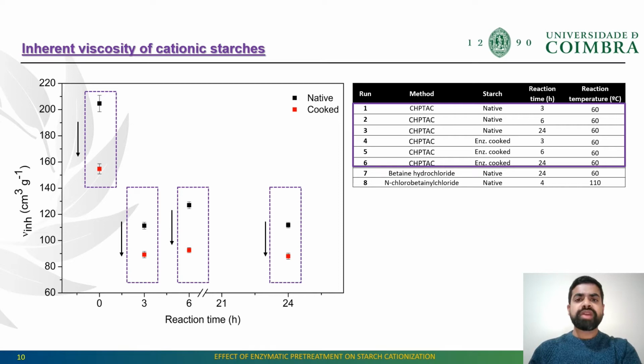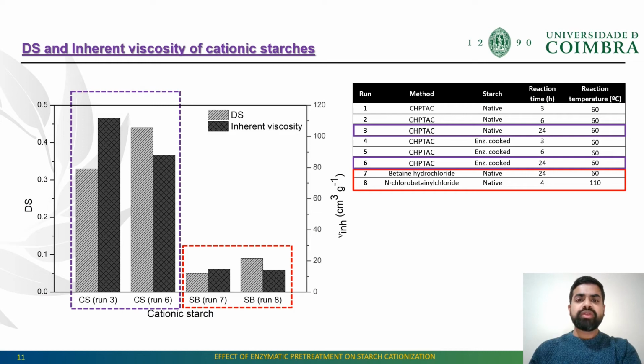The effect of reaction time on inherent viscosity was also studied while performing the reaction for 3 hours, 6 hours and 24 hours. The figure shows the decrease in inherent viscosity at 3 hours. Further, at 6 hours, viscosity increases slightly, but it further reduces while the reaction continues until 24 hours. The inherent viscosity was also measured for the starch betainates obtained from the esterification reaction in runs 7 and 8. The figure shows the comparison of starch betainate with other cationic starch ethers from runs 3 and 6.